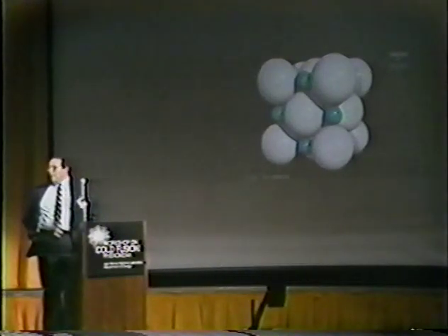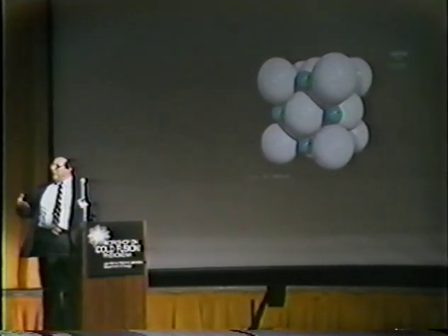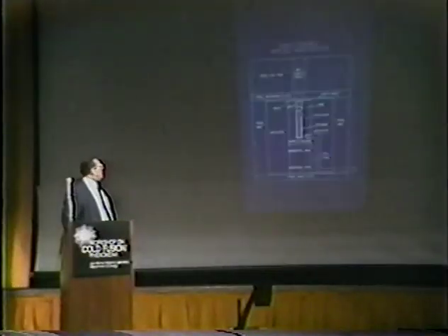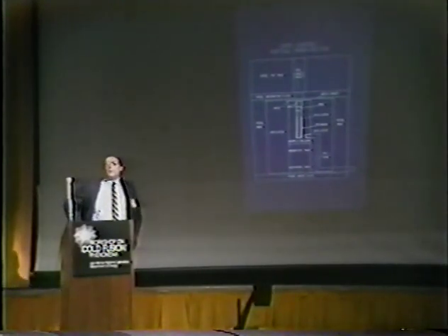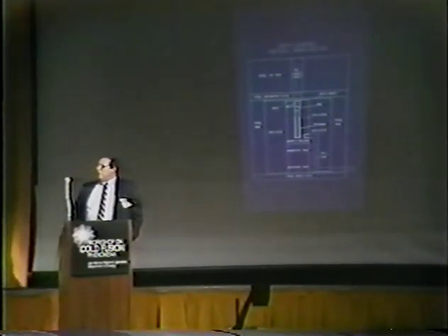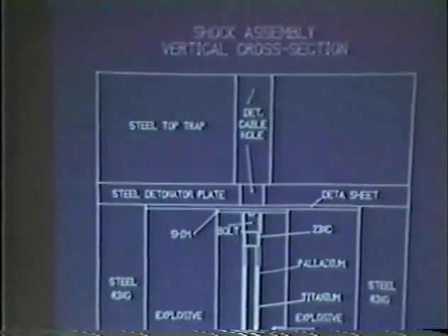We also had in the experimental chamber, as I'll show in a moment, titanium, 1/10 of a gram of titanium and 3/10 of a gram of palladium. The titanium was also deuterated to approximately 7/10 of a gram, 7/10 deuterium per metalloid site. In the next overhead, or slide, we show the experimental chamber of the fully shock-loaded recoverable system.